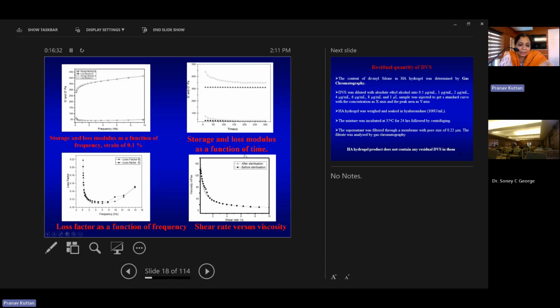And again, the same modulus was monitored against time, and it is showing a comparatively stable kind of behavior. Again, the loss factor, which gives an idea about the stability of the hydrogel, was plotted, which is found to be lesser than 1. That means it is a stable, elastic kind of a material with elastic properties dominant in that. And also it shows the shear thinning behavior, which will be helpful in giving it as an injection.